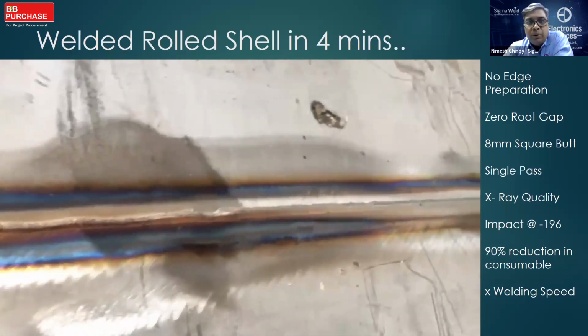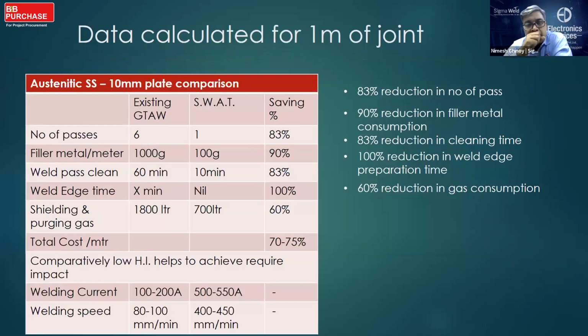Let's compare data for about 10 mm thick plate. Using an existing TIG welding process, you would need 6 passes to do it. Using S.W.A.T., you could do it in a single pass. Using filler metal, you would need about 1 kg. Here, you would need only 100 grams. Cleaning, you would need about 60 minutes. Here, you need 10 minutes per pass.